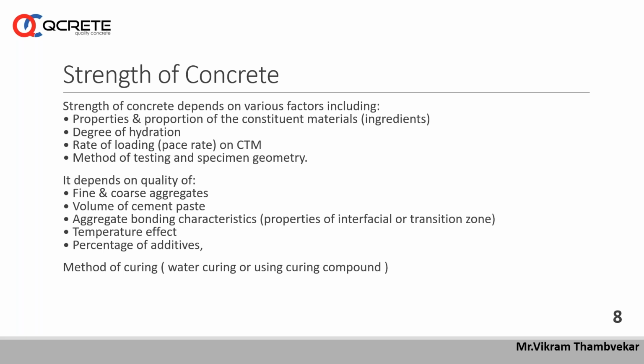The temperature effect and percentage of admixtures are also very important factors for making fresh concrete. Because I have observed at one site, one very reputed company and reputed concrete supplier, a higher grade of concrete was used, and there was no final setting for more than 30-40 days or 60 days. When we saw that final setting had not taken place, we came to know that it happened because of the excessive use of chemical admixture. So the use of chemical admixture should be restricted, as per compatibility of the concrete itself. For higher grade concrete, it is necessary to conduct trials at site, and then go for making fresh concrete for regular use in framework.